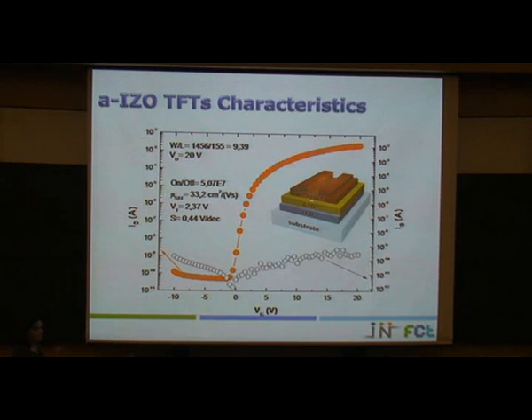So, what is the difference? It is exactly the conductivity. For the channel layer, the amount of oxygen is higher than in the case of the drain and source. So I use the same sputtering machine, but I change the amount of oxygen during the deposition. For the channel layer, I need to have a higher resistivity, so the amount of oxygen is higher. For the source and drain, the amount of oxygen is lower, so the film conductivity is higher. But this is very interesting because I can use the same target and I play with the deposition conditions, and of course the oxygen is crucial.